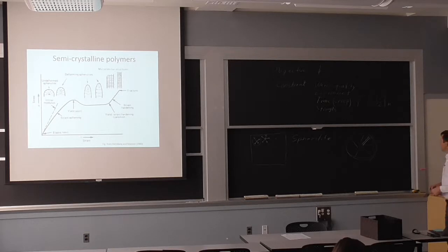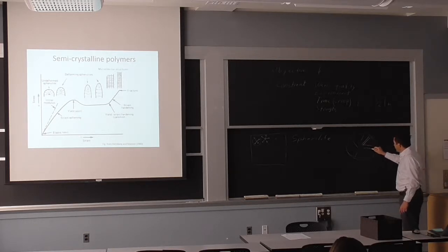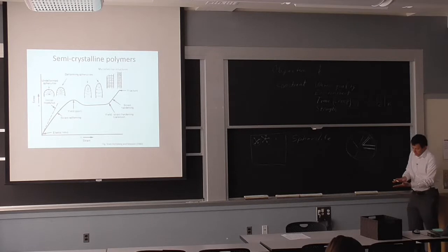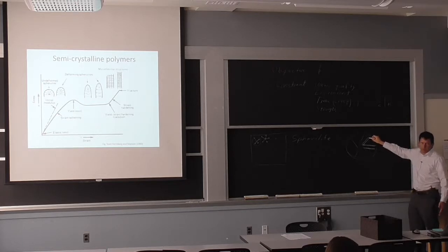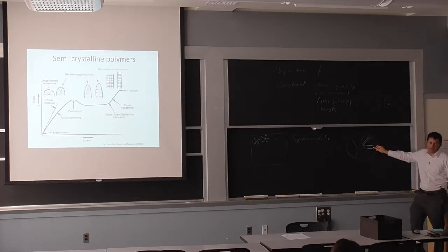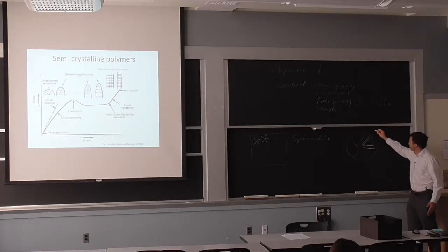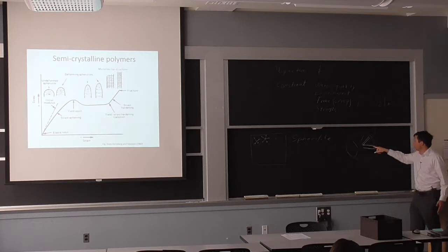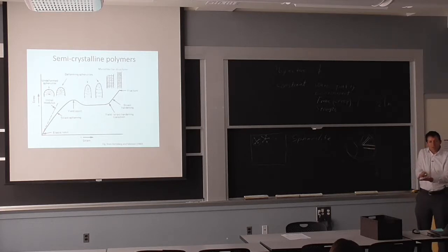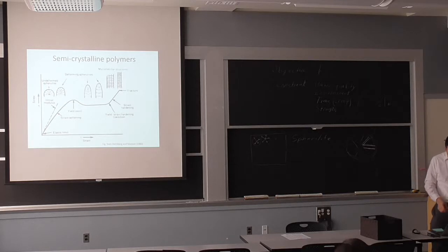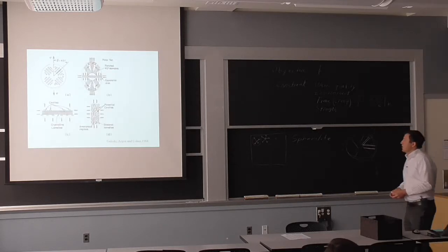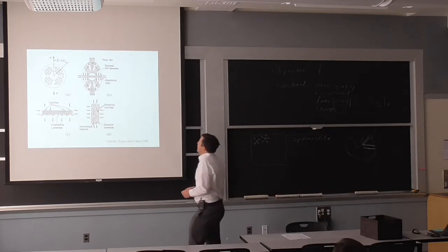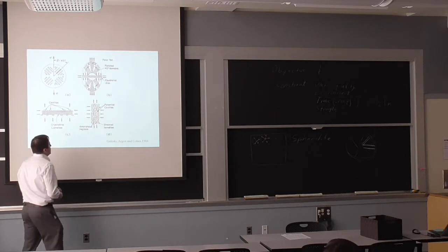And we'll go to, well, you could probably start thinking, if I'm pulling on this and I'm here, this is the opposite situation. I got 2 crystallites and I got an amorphous material in between. So if I try to pull it, there's going to be a likelihood to start forming voids. So if the plastic deformation starts here, the void formation, if I have craze, if I have stress whitening, it's typically going to happen. So this was the loading direction here. So it's going to happen on the plane here perpendicular to the loading direction. I've got 2 stiff components. I'm trying to open it up, and it's very easy to get a hydrostatic pressure tension there. So, I did have a more detailed view here of how you can start deforming and eventually break down what you had as crystalline structure and turn into the new crystalline structure.